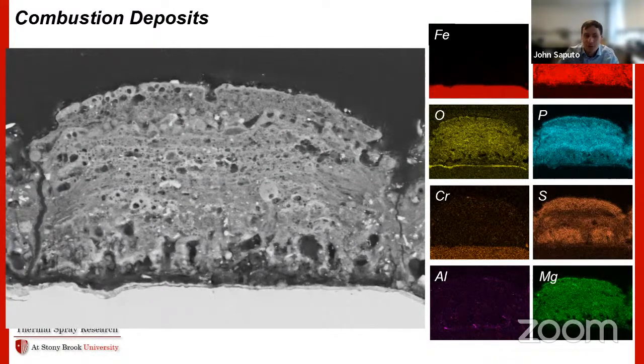So this is inevitable. This isn't something that you're going to be able to get to go away with the coating. It's not necessarily something that happens specifically because of the high temperatures. It's just the way of life in these systems to have this kind of buildup happen over time. So you can see the oxide scale here is actually pretty thin. It's this yellow map. It's about a micron thick in this region that it looks to be detrimental in. So that's not actually that bad.